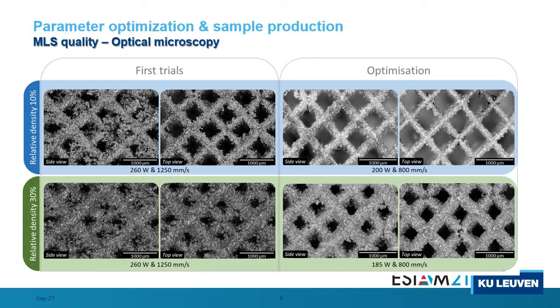The main results of the parameter optimization process are presented in these pictures. On the left side, the first trials are presented. For these coupons, we used high laser power and velocity. The resulting quality is very poor, with severe dross formation affecting the outer surface of the struts. Moreover, looking at 30% coupons from a side, it is almost impossible to clearly distinguish a strut.